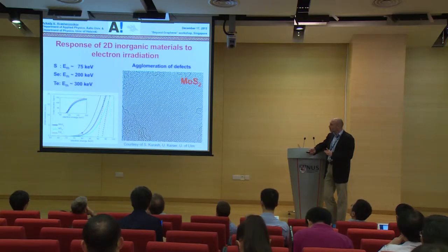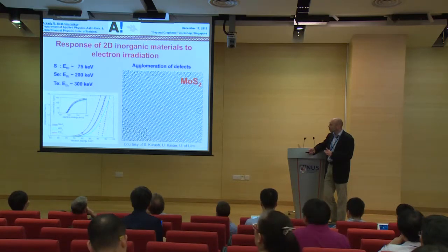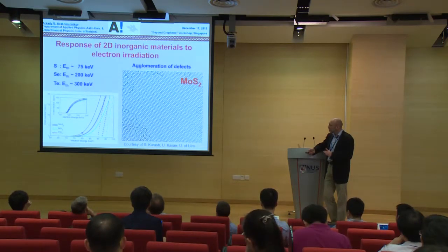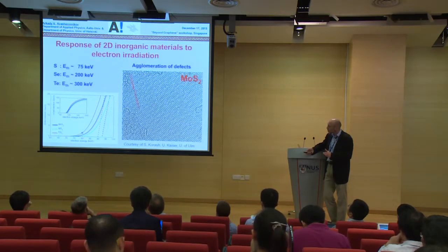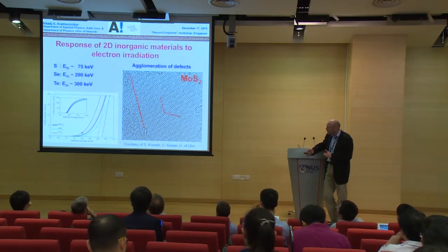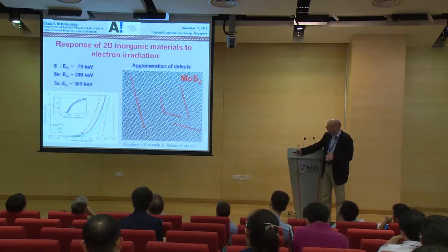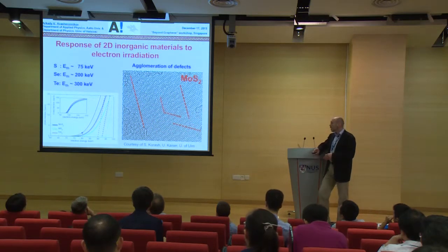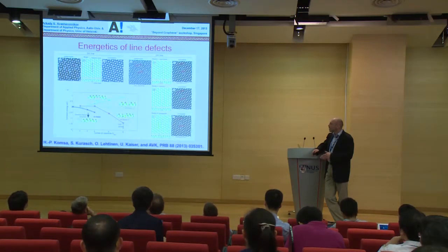Now let's put a sample into the TEM and keep it under the beam for some time. This is the movie, and you may see that some linear structures appear, like this, or like that, here again, another one here, and one will appear also there. I hope you can see them. These are, in fact, vacancy lines. Vacancies tend to agglomerate and form lines. Vacancies can agglomerate in different configurations.